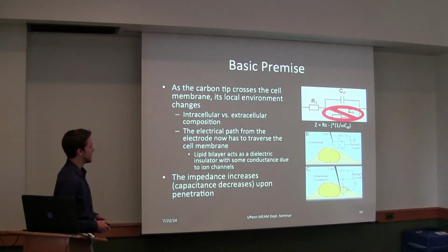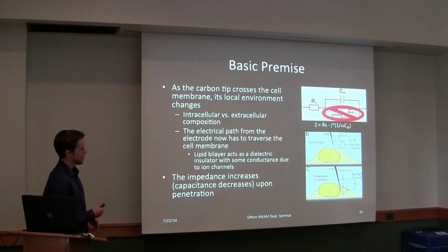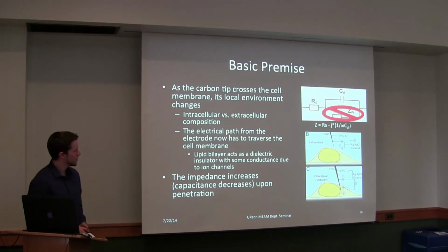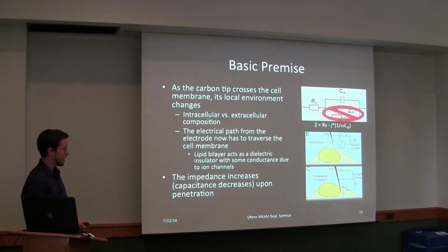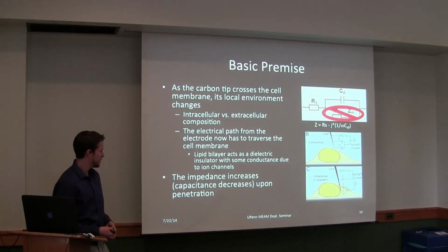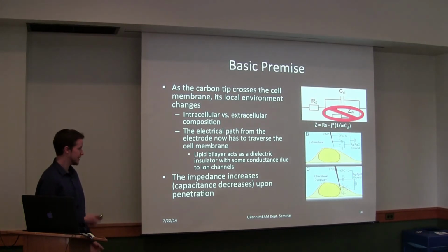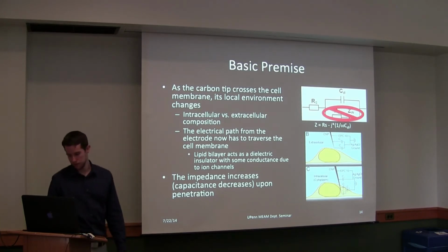So the basic premise of our scheme is that as the carbon tip crosses the cell membrane, changes in the local environment cause a distinct change in the impedance signal that we get. So again, we have this RC circuit. The impedance is basically the real part is due to the resistance, the series resistance. The imaginary part is due to the capacitance. And we can look at changes in these parameters as the CNP penetrates the cell. So you have differences both in extracellular versus intracellular composition, and then you also have that the electrical path now has to traverse the cellular membrane. So the lipid bilayer acts as a dielectric insulator. It has some conductance due to ion channels, but it mostly acts as a capacitor. And we get this impedance increase and corresponding capacitance decrease, since they're related, upon cell penetration.